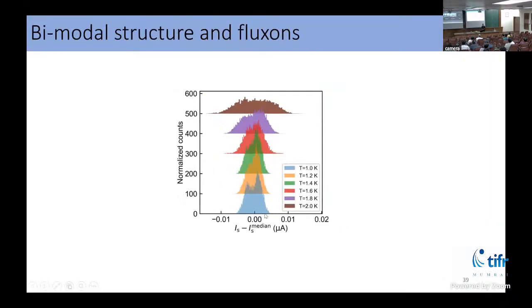Yeah. So basically, you saw that at low temperatures, the histograms were unimodal. But as I increase the temperature, you saw up to 1 Kelvin, they become sort of bimodal. And what we saw even further was that if I keep on increasing the temperature, this bimodality sort of spreads. And at the end, what you get is a much, much wider distribution. Now, how do I explain that?